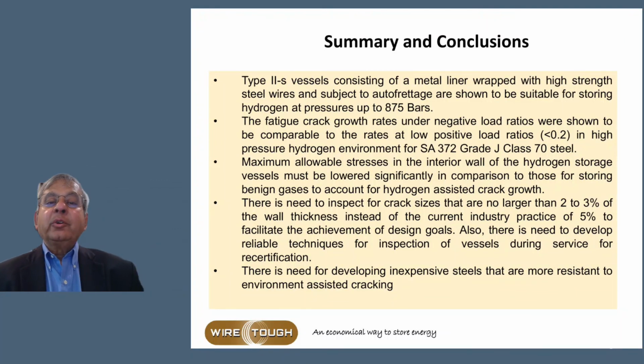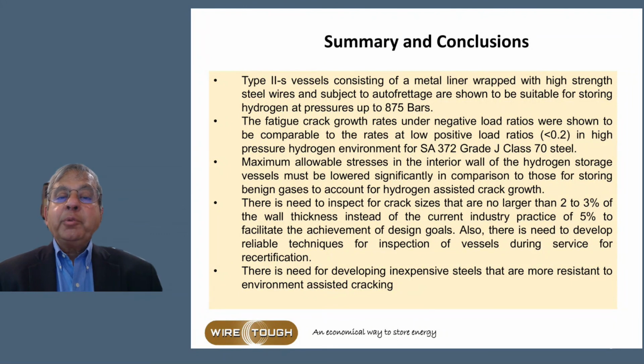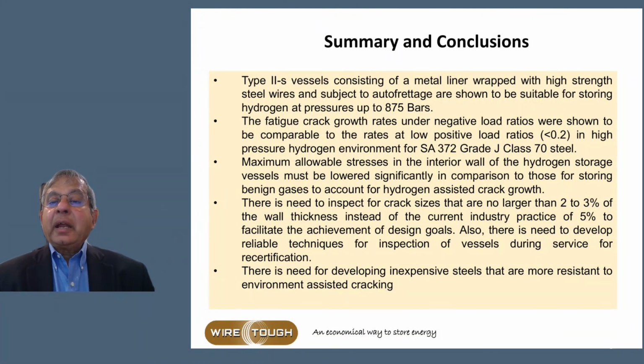So with that, I would like to move to the summary and conclusions. Type 2S vessels consisting of a metal liner wrapped with high-strength steel wires and subjected to autofrettage are shown to be suitable for storing hydrogen at pressures of up to 875 bars. The fatigue crack growth rates under negative load ratios were shown to be comparable to the rates at low positive load ratios of less than 0.2 in high-pressure hydrogen environment for SA372 Grade J Class 70 steel. I also want to point out that I've been using A372 and SA372 interchangeably. A372 refers to an ASTM standard, and SA372 refers to an ASME standard for the same material. So we can use those terminologies interchangeably.